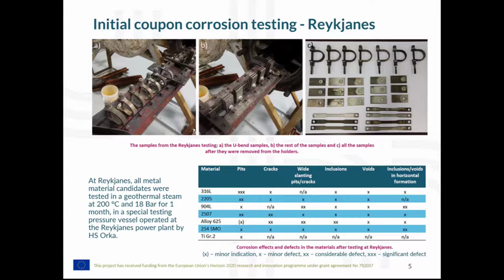So let's go through the initial coupon corrosion testing, starting with Reykjanes, which is a geothermal area in southwestern Iceland. There we tested all the metal material candidates in geothermal steam at 200 degrees, 18 bars for 1 month, in a special testing pressure vessel, which is operated by HS Orka at Reykjanes power plant.